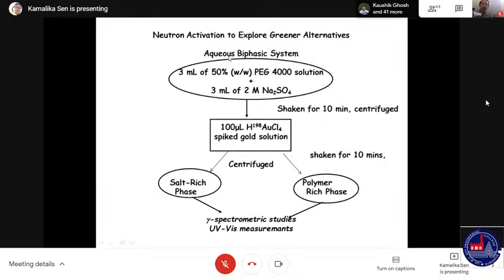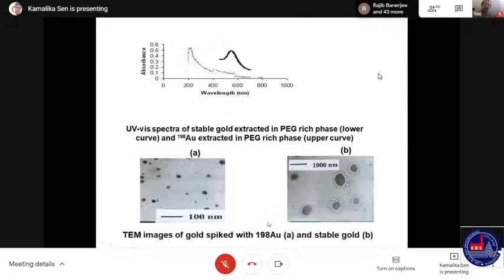The simple setup of gold nanoparticle extraction was a 50% polyethylene glycol water solution, mixed with sodium sulfate solution, and that was shaken with gold-198 aurichloride salt solution. I was trying to separate the salt-rich and polymer-rich phases and do gamma spectrometric analysis, but it made nanoparticles, and we had to settle it for 5 days so that the radioactivity decays out. Then we put it into the UV-visible spectrophotometer, which shows a characteristic surface plasmon resonance peak, and the TEM images showed 20 to 30 nanometer sized particles.